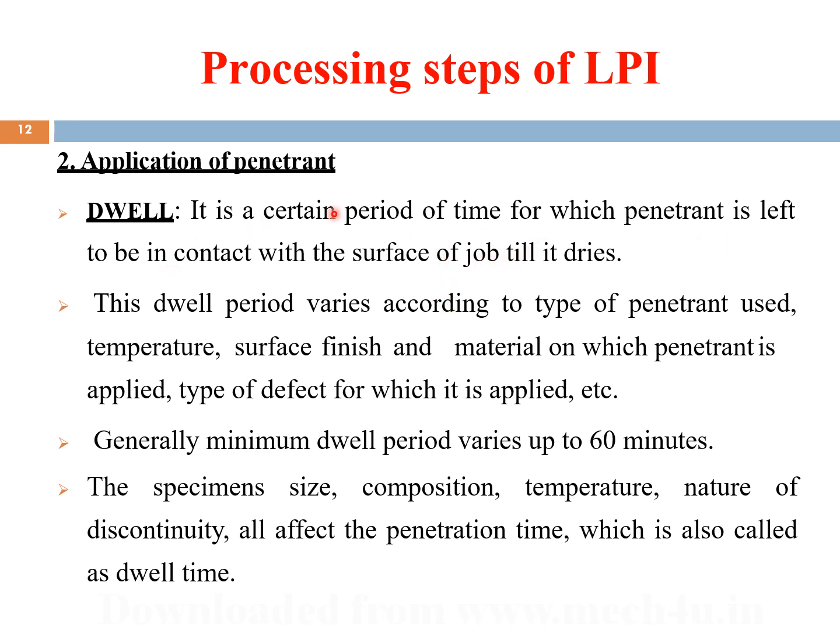This dwell period varies depending on the type of dye or penetrant used, the temperature at which it is inspected, the surface finish, the material on which the penetrant is applied, and the type of defect being looked for. Generally, the dwell period or waiting period for the penetrant to enter all the cracks is up to 60 minutes.